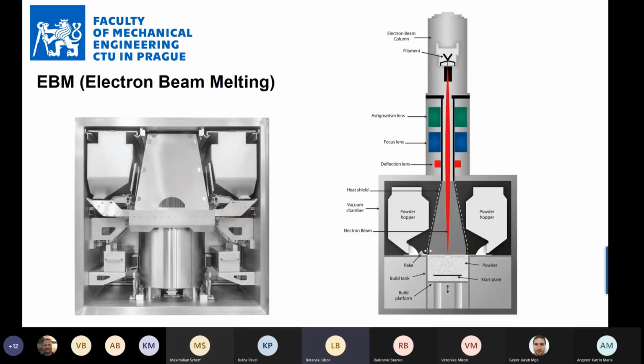Now I would maybe aim for the application and for the difference between direct metal laser sintering and electron beam melting. This is the technology which has a lot of benefits over direct metal laser sintering, because in the aerospace industry, maybe the first aspect they need to solve is material properties, of course. So when they are printing reactive materials, titanium alloys typically for compressor blades, they are valuing the fact that you can use the electron beam only within the vacuum, and the vacuum itself is protecting the material. So this is one aspect which is quite good on electron beam melting. The second aspect is that you can really preheat the chamber to very high temperatures, as I mentioned, 1000 degrees Celsius. So then you have minimum residual stresses.